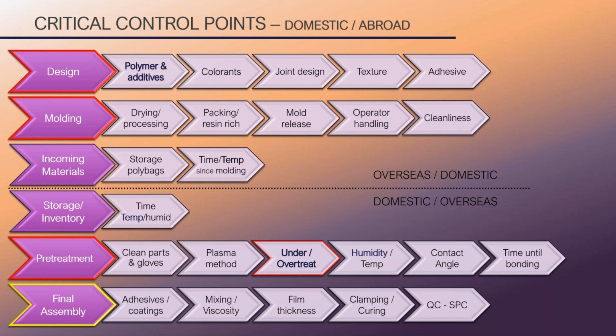In this particular case, humidity conditions during pretreatment, certainly of atmospheric plasmas, affect the level of pretreatment more than temperature. So keep in mind, humidity has the most effect on the actual pretreatment. Temperature has an effect on the migration. We also want to make sure that we've achieved the proper contact angles and the amount of time until bonding.